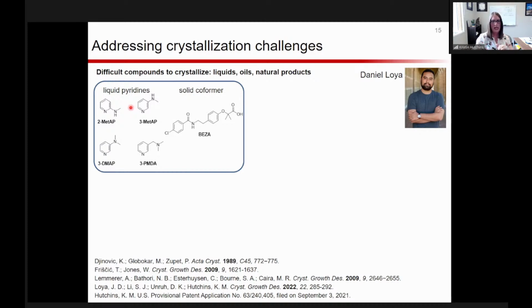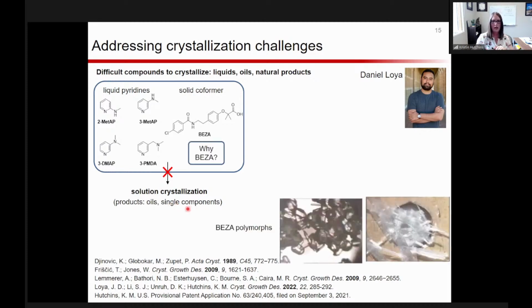And so we had chosen the ones I have here on the screen, and these are actually liquid pyridines. So when Daniel was trying to do co-crystallization in solution, we kept getting oils of these compounds out. And we also would get single components out. The reason I decided to stick with this is that bezafibrate is actually a molecule that really likes to crystallize by itself rather than co-crystallizing. And so the beza actually crystallizes in two known polymorphs, and you can differentiate those nicely by just looking under an optical microscope. One is sort of blocky and the other one is sort of needle-like.